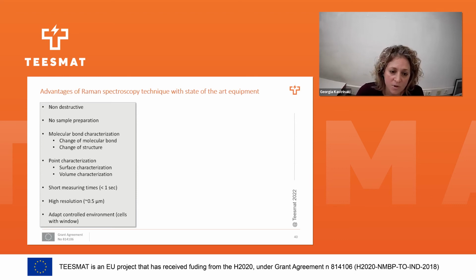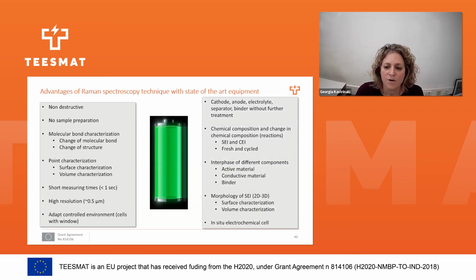It's characterized by a short measuring time, so we can have one spectrum in under 1 second, and we can also have a high resolution, measuring down to 0.5 micron. We can also adapt the environment in which we want to study our material, because we can have cells with an optical window, as I showed you. So for battery studies, we can study the cathode, the anode, the electrolyte, the separator, and the binder without further treatment. We can study the chemical composition and its changes, so we can see what kind of reactions are taking place on the electrodes.